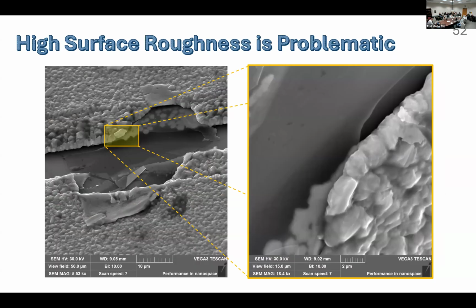And the other way I can tell is that, in this case, this was before I did the mask. In this case, I simply used the common method of depositing metal, where I used the shadow mask. So you can see here that this is the flake with metal on top of it that I deposited with e-beam evaporation. So you see that the copper only grew on the flake where the flake had metal, not on the side where the flake didn't have any metal. So that's another way I can tell that it is only depositing itself on the metal sides and not on the flake itself.